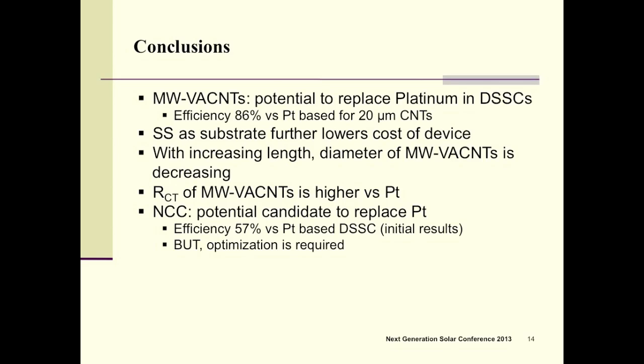So in conclusion, multi-wall vertically aligned carbon nanotubes have potential to replace platinum. It has given us efficiency about 86% of that of the platinum-based dye-sensitized solar cell. Stainless steel as substrate further lowers the cost, because one of the expensive components in a dye-sensitized solar cell is the FTO, the transparent conducting oxide substrate. And with increasing length, the radius of the multi-wall carbon nanotube is decreasing, and charge transfer resistance is higher as compared to platinum.